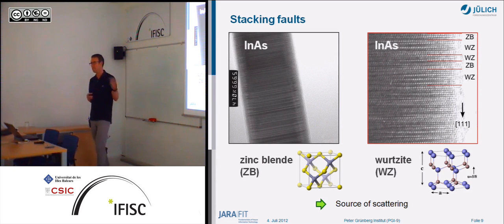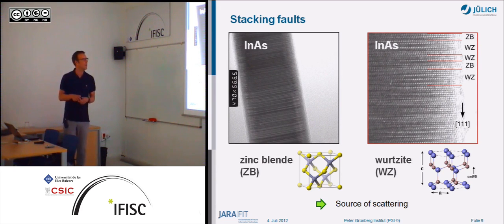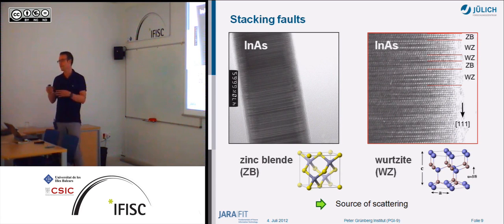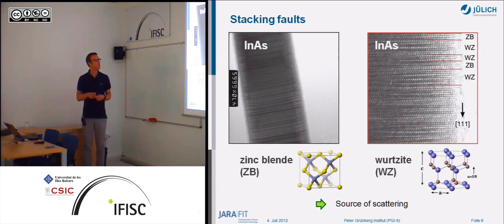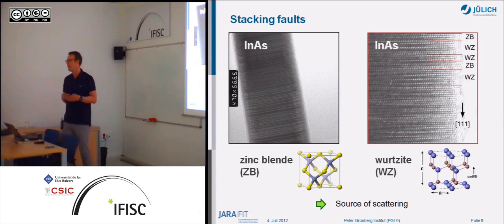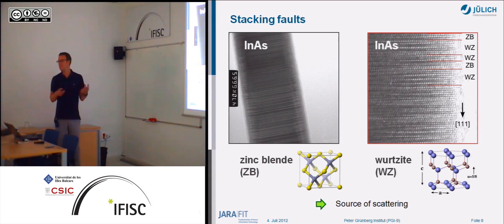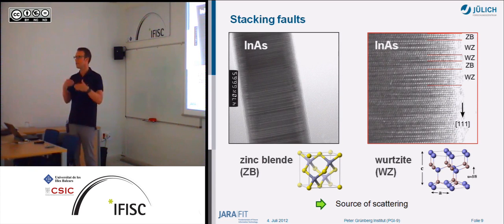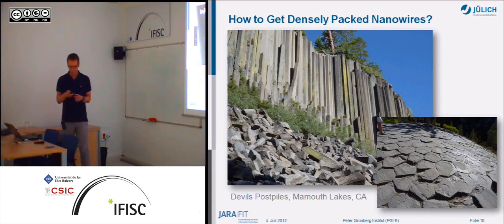So there's a competition between Wurtzite and zinc blende, and in fact both happen in the nanowire. The nanowire decides by accident or by energy reasons what is growing in this area, Wurtzite, zinc blende, and so on. So there's a statistical switching between both crystal configurations. And of course, one has to take this into consideration. This might be a source of scattering, because we have different band gaps in both crystal configurations, and so the potential profile isn't that smooth.